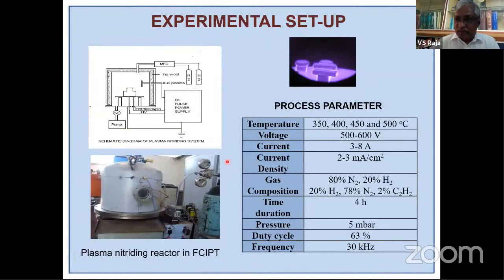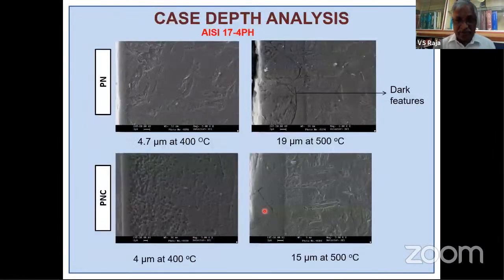But the thickness of these coatings is very small. For example, for body implants, small coating thickness is fine. But I want to talk about gearboxes, where the thickness of the coating is quite large. Then plasma ion implantation will not work. Then you go for the plasma nitriding technique. That is there in the Plasma Institute in Gujarat. In fact, it has been helping aerospace industries, even oil and gas industries, thermal industries, nuclear industries, to a large extent to convert the surface into a hard, corrosion-resistant surface.